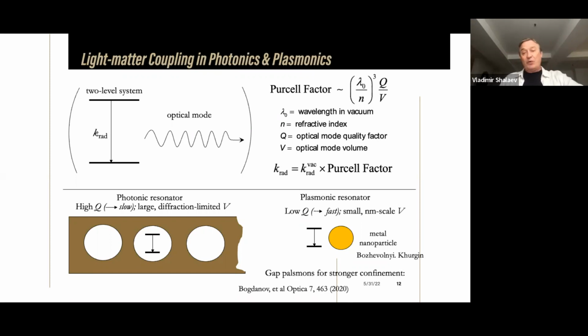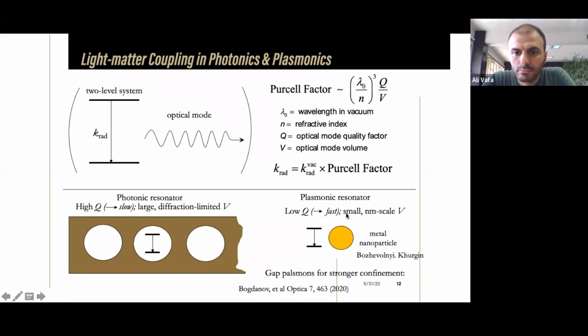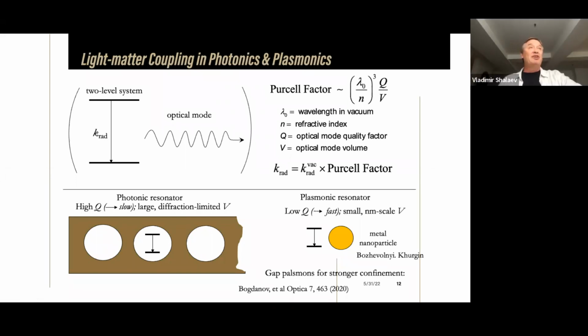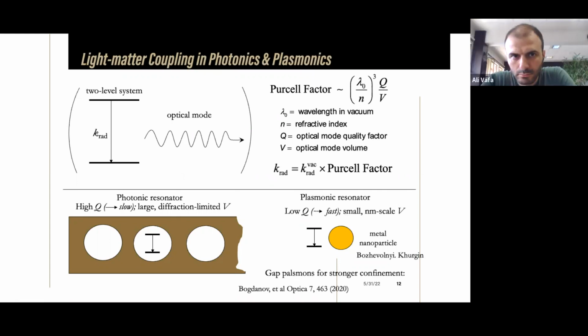So could we go the other way without sacrificing the speed? And that's exactly where plasmonics comes in handy. For plasmonics, the quality factor is relatively low, 100, but the volume could be exceptionally small, as I pointed out, like let's say 5 nanometers. 5 nanometers is 100 times smaller than the wavelength. So you have to raise it to the power 3, which gives you 1 million. You get an increase by a factor of a million only because of this exceptionally strong confinement of the electromagnetic mode. And quality factor Q of 100 means that it's an additional enhancement. So you end up with the same enhancement.